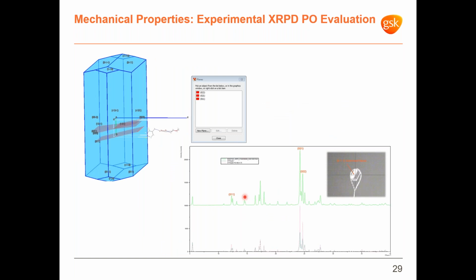And while morphology modeling is very useful for providing attachment energies and confirming the relative orientation of crystallographic planes under stress, assessment of preferred orientation in XRPD patterns is a very effective tool to monitor preferential breakage direction of the crystallites in a powder, for example, during milling. In the case of our study API, PO assessment confirms preferential breakage along the plane perpendicular to the 011 direction. That is the plane with the second lowest attachment energy, as we observed in the previous slide. This is somehow not what we would have expected in the first place, but can be rationalized, I think, when considered in combination with the rugosity values of the two planes.